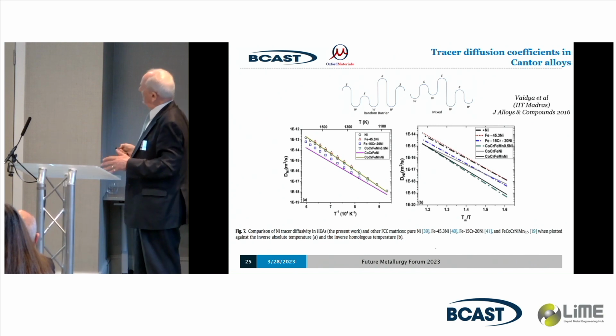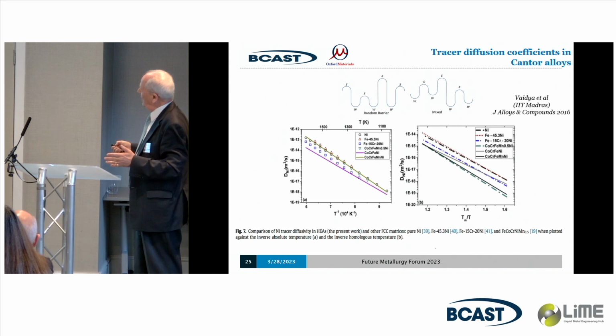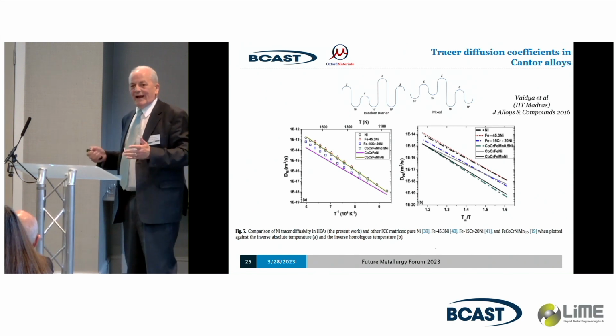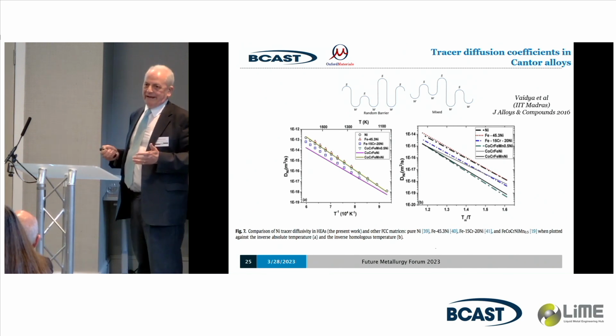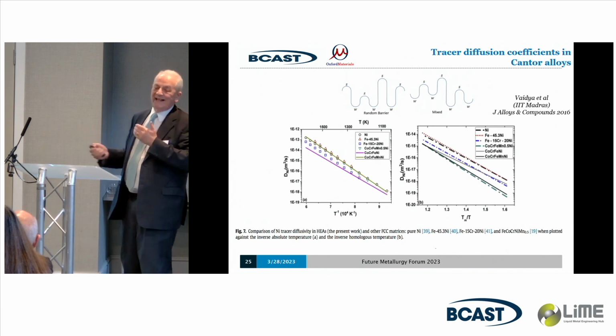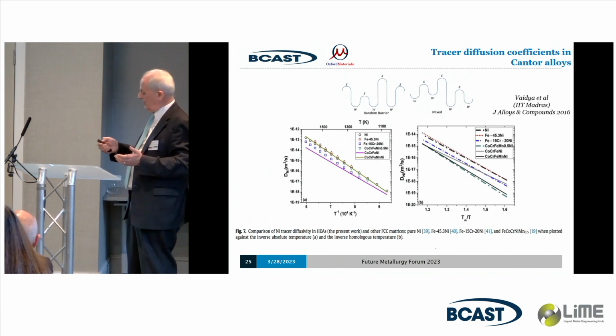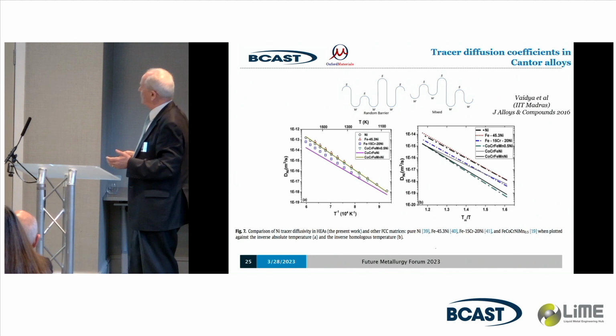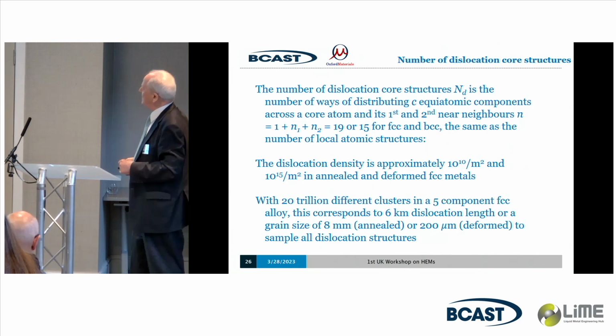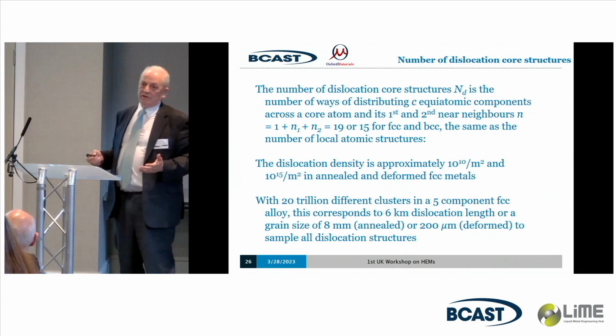That means that the vacancy gets stuck in a certain place where there's a low energy, and it doesn't move around so much, and so the diffusion rates go down. You can't guarantee exactly which alloys they'll go down or by how much, but the only really good studies are by tracer diffusion, and here you can see about an order of magnitude reduction compared to a single, simpler FCC material. Dislocations, same thing.